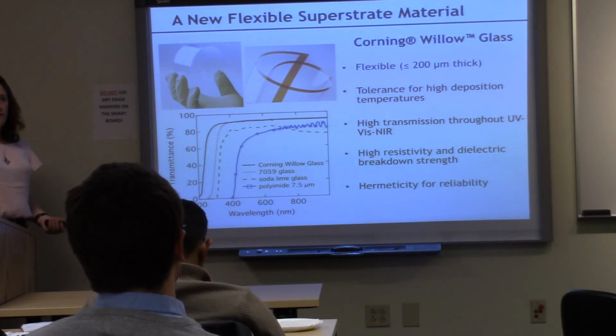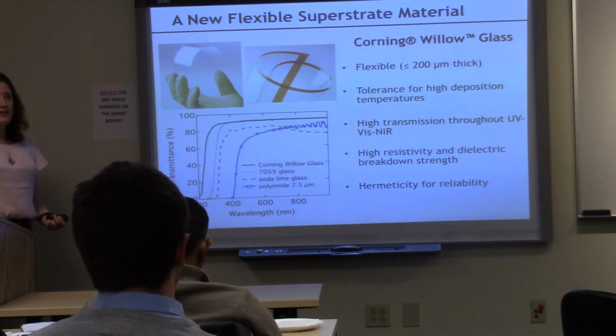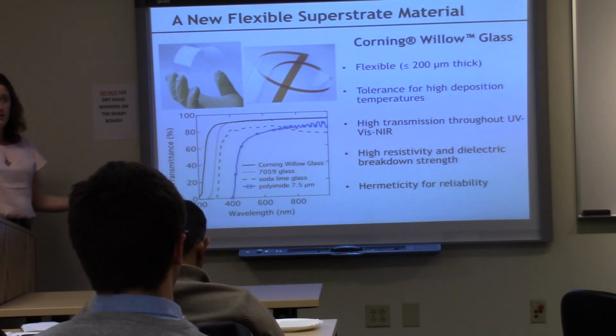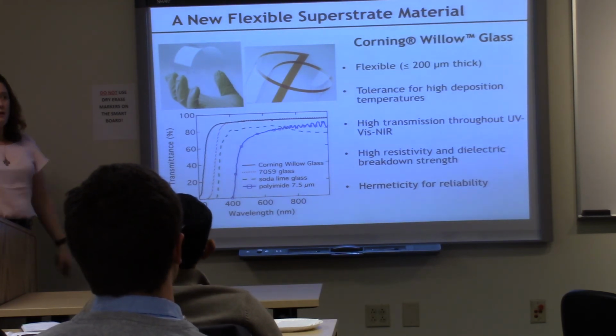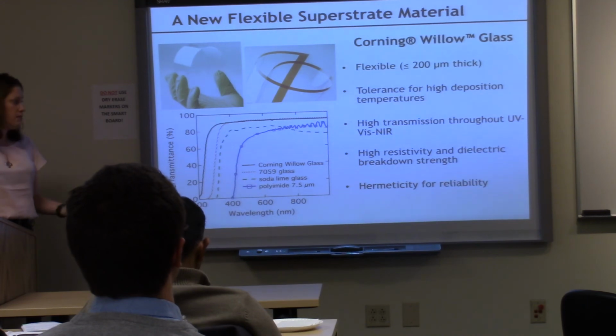Which means if you have a big string of modules and you put them together, they're usually wired up in a way where you're going to end up with a very high voltage on the end of that string. And this is actually one of the things that limits module glass thicknesses and weights, is that you've got to have a thick enough piece of glass to make sure you don't shock the guy who's dumb enough to touch the module on the end. You have to have a product that's safe. And so here we can actually meet that with a 100 micron thick piece instead of a 3.2 millimeter piece of glass. Actually pretty cool.